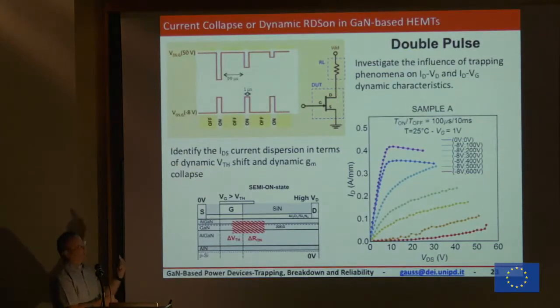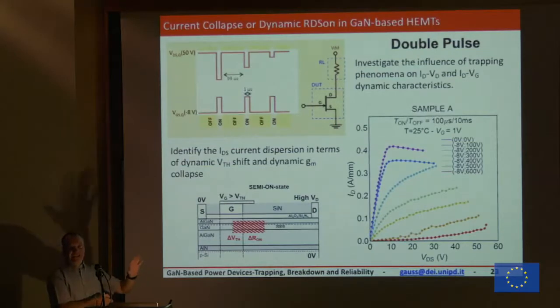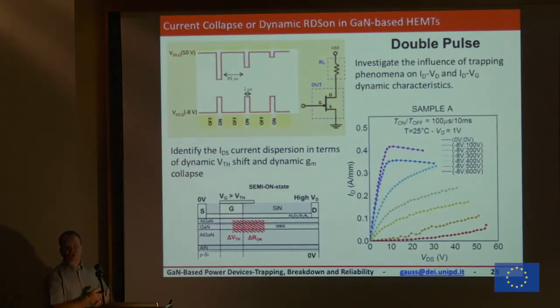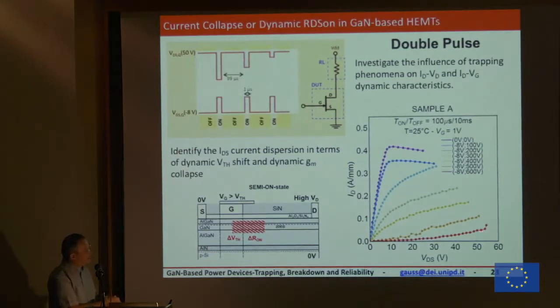And when I turn on my device, I go to the on condition. I measure the device after a few microseconds. The electrons are still there, and they keep my device blocked. So I see less current than what I expected. And this is what we call current collapse. And if I increase the voltage in the quiescent bias point, like 600 volts, you see here, -8. So I am having the bias point in this condition at a very high VDS. The trapping is huge. And when I try to turn on my device, I see the device completely collapsed, and I see these curves. So this is really the current collapse.